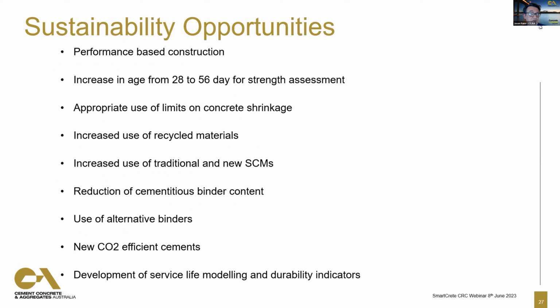Looking at limits of concrete shrinkage and making sure that they're applied where you need those limits, where otherwise the structure will have cracking or shrinkage that's not acceptable. Opportunity to use more recycled materials from different streams, increase the use of traditional SCMs and introduce the use of new SCMs, reduce cement contents where possible, and have the ability to use alternative binders, including these new CO2 efficient cements such as LC3s and things like that.